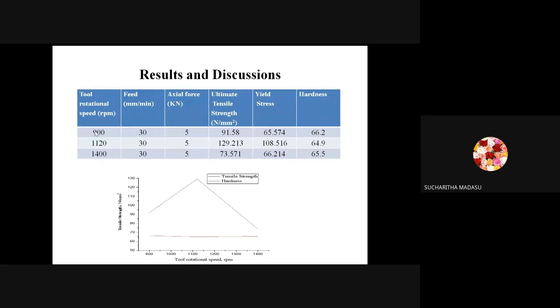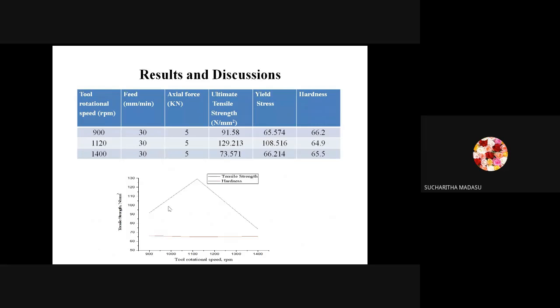Here I am showing my values. 900, all these are constants. And the ultimate tensile strength here I am getting as 91.58, hardness as 66.2. As I told, at moderate tool rotational speeds we are getting high tensile strength compared to lower speeds as well as higher speeds. When I am plotting a graph of tensile strength and hardness against tool rotational speed, I have taken tool rotational speed on the x-axis and tensile strength on the y-axis. Here we can see that at moderate speed only the ultimate tensile strength is more, and when we increase the tool rotational speed, the tensile strength gets less.